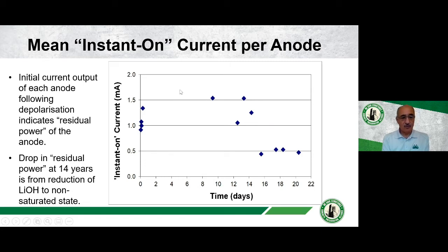One other thing that we were measuring, which turned out to be quite a useful parameter, was what we call the instant on current. When we finished with our depolarization at 24 hours and the anodes were off, when we turned them back on, we measured the current output within 5 seconds of turning them back on. We call that the instant on, and that represents the power of the anode at that particular time. So, how much current it is capable of producing when you first switch it on. We could see that we could get more than 1 milliamp per anode for most of its life, but at around 14 years, which is the time when we think that the lithium hydroxide was consumed, or at least went to non-saturation conditions, that current output had diminished considerably. So this gives us a profile of how the anode power lasted over the years.